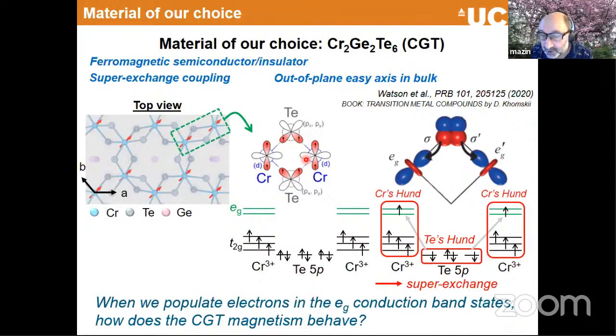Similarly, for exchange, again, as Daniel also pointed out, we understand very well how this exchange anisotropy comes for the 3+ case, and it's Ising anisotropy. And if you have a band structure calculation, it's no problem whatsoever to separate exchange anisotropy from single-site. I don't understand why your colleague didn't do that. It's completely elementary. And you can also see from that whether it's a metallic effect or not. I strongly suspect that everything you see is related to metallization and nothing else, not on the level of this diagram. And in fact, what you told us is that it's very strong doping. It's really supposed to become a very good metal if it's 0.25 electrons per chromium.